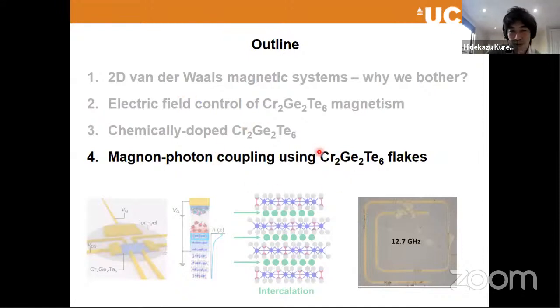And finally, I probably spent 5 minutes to explain this one. This is just quickly flashing you the results, but I hope that can generate some interest among some of you in the audience. The idea is very simple, because when you exfoliate the flake, so this is one of the flakes, you can see that the size of this flake is very small, micrometers in the lateral dimension, and the thickness is as thin as 1 nanometer. So that's a significantly lower magnetic volume. And if you want to sense this small magnet by a dynamic experiment, you have to have a very small mode volume of the resonator.